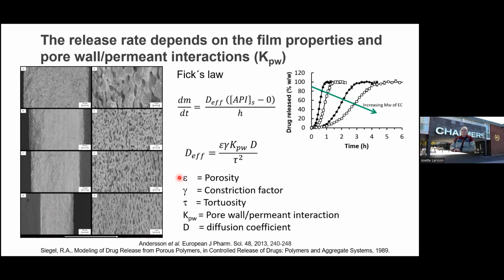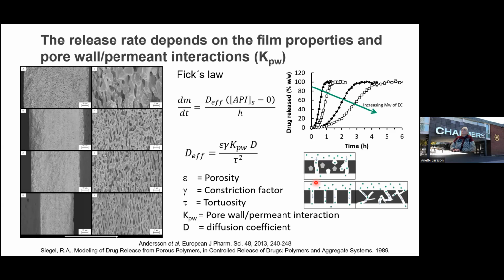So the effective diffusion coefficient depends on the porosity, so how many pores you have, but also how these pores are connected. So the connectivity here, or constriction factor, and also tortuosity. If you have a straight pore, you have this length you should pass. If, as you always have, there are bends in the pores, then they will take different ways, and that is called that they have different tortuosities.